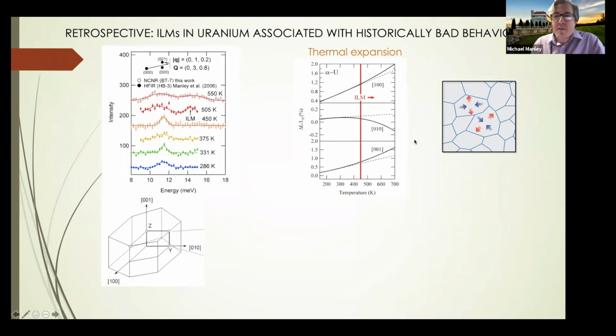But what this has in effect, if you think about mechanical properties, is that if you put this in a polycrystal, one grain could be adjacent to another grain, where one of the grains wants to contract and the other grain wants to expand. Okay, and when you change temperature, they're attached, so they become stressed, and stress builds up.